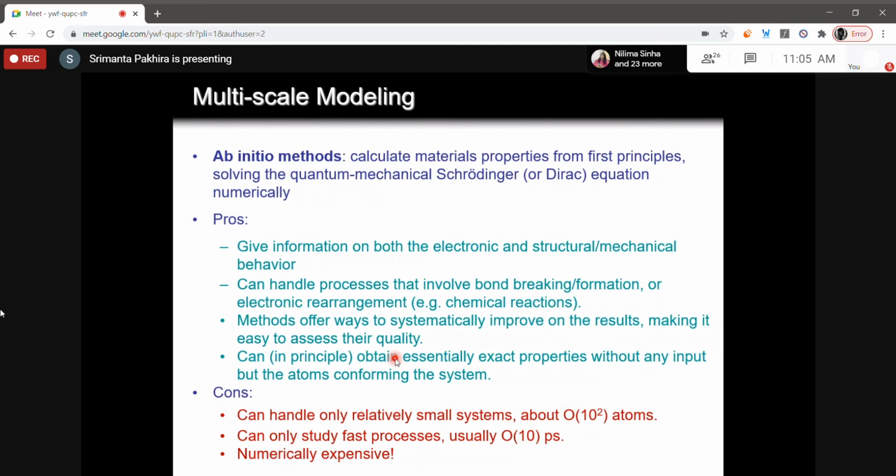When we start the calculation, we need a very big cluster, a supercomputer, many things. But using that, on the order of 100 to 200 or 300 atoms we can consider. I have a system with 120 atoms. I remember the density functional theory optimization I did using a supercomputer took 6 months. So there is of course a limitation. Maybe 1,000 atoms we cannot impose for the ab initio methods.